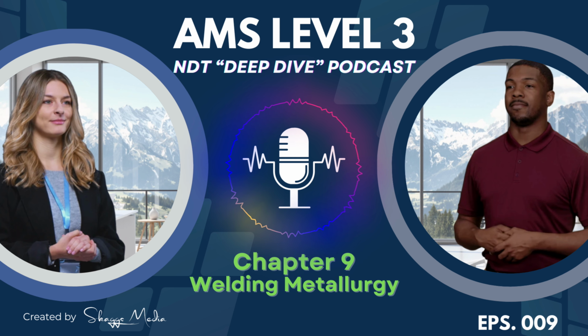What's the other big issue with welding stainless? Something called sensitization. Yes, sensitization, which leads to intergranular corrosion attack, or IGA. This is a major concern for corrosion resistance after welding. It happens if the austenitic stainless steel is heated or held in a specific temperature range, roughly 800 to 1600 degrees Fahrenheit. This happens, for example, in the HAZ during multi-pass welding.